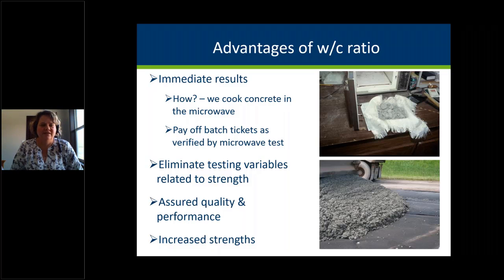Why do we do that? Because we know right away in the field what kind of a water cement ratio we actually have. We pay off the batch tickets verified by the microwave, so we are paying off the contractor's batching data. There's a little bit more involved in our spec, but the whole idea is that we're paying off of a water cement ratio and we're paying the contractor based on the concrete they're producing, not waiting 28 days for